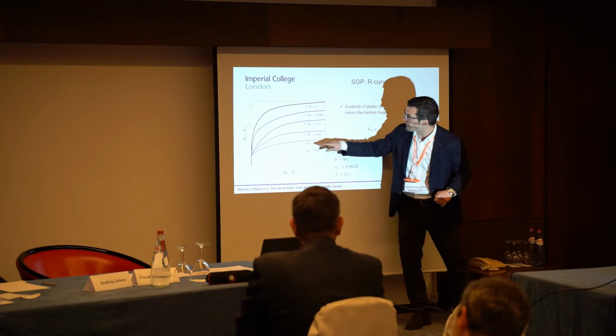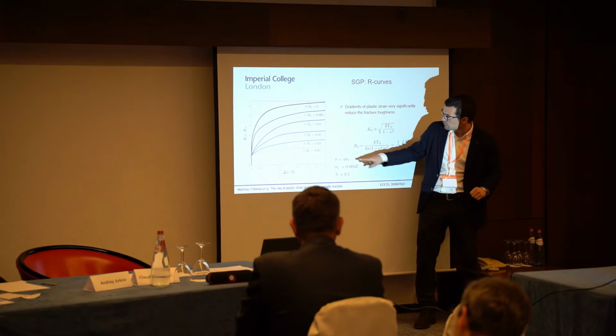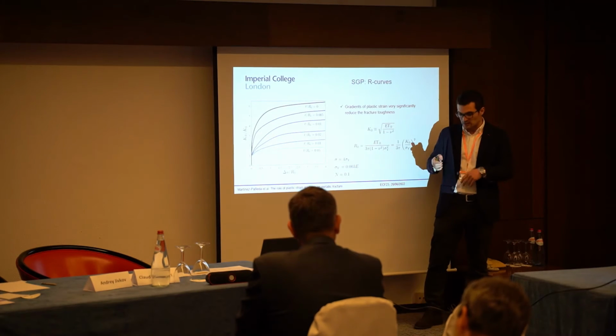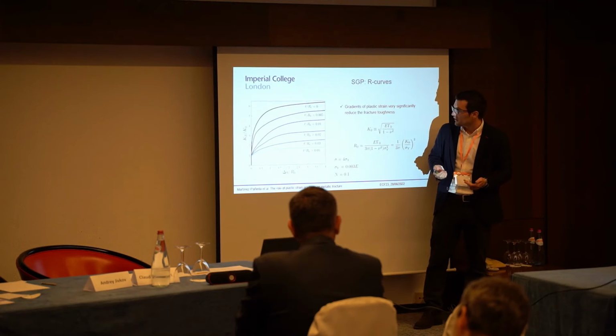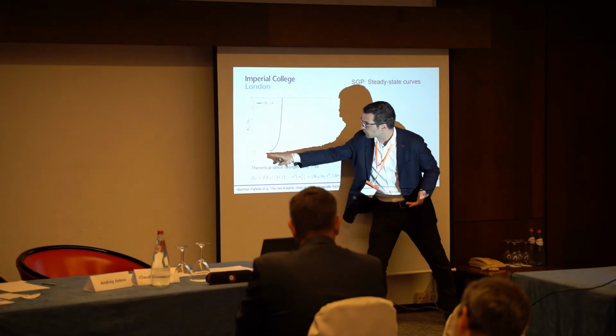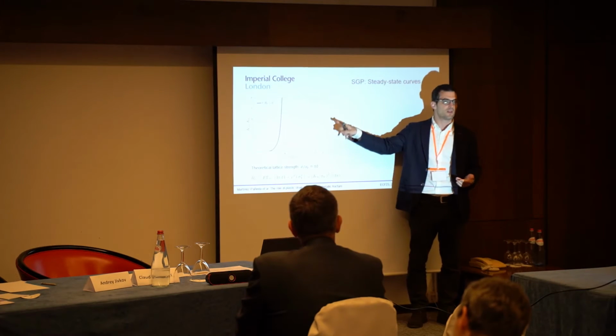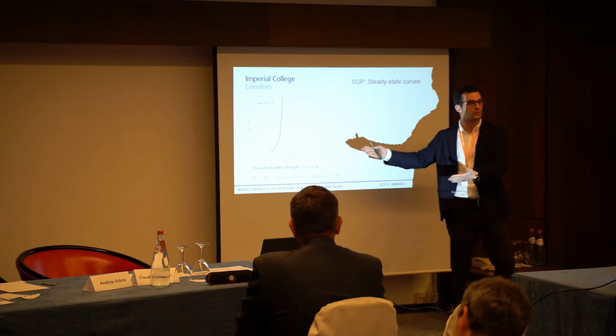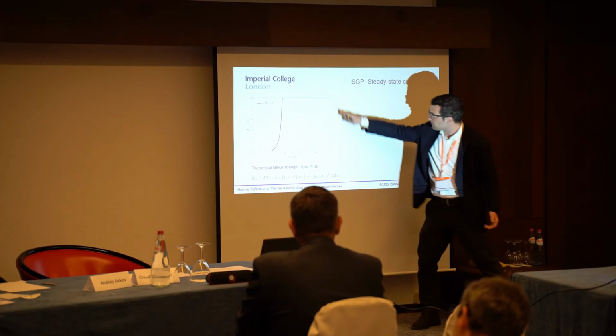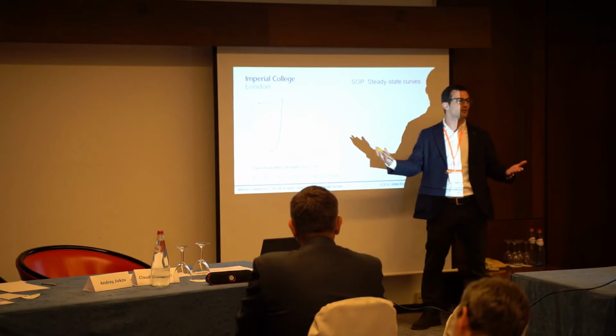So we can compute this steady state fracture toughness as a function of the cohesive strength. In this case, it's 4 times the yield stress, but we can move around. And as I told you before, the regime that we're interested in goes all the way to 10 times the yield stress, because this is the theoretical lattice strength, this is the cleavage strength, this is the level that you need to reach if you want to predict brittle fracture.